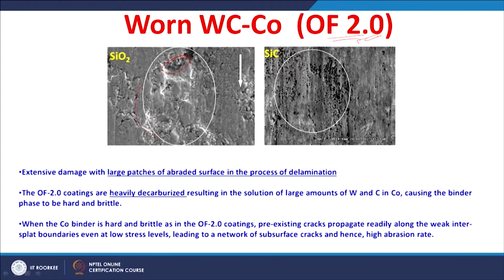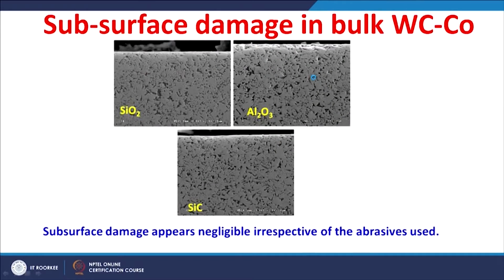So, when you have a decarburization maximum, which we found at the oxygen to fuel ratio of 2.0, you see large patches of material and then their delamination. The subsurface cracking can also be understood. So, you can see the bulk tungsten carbide cobalt subsurface damage.